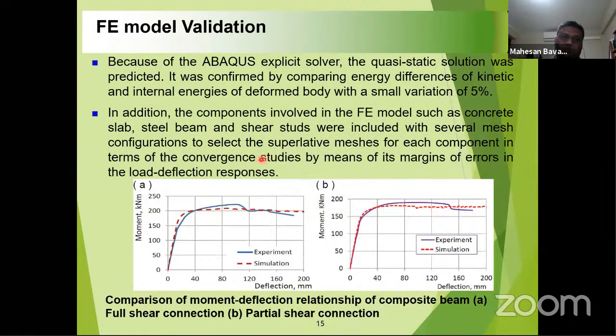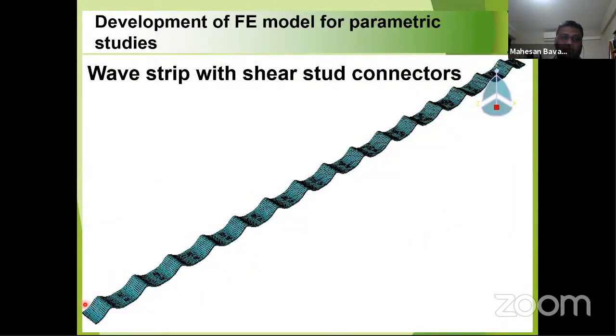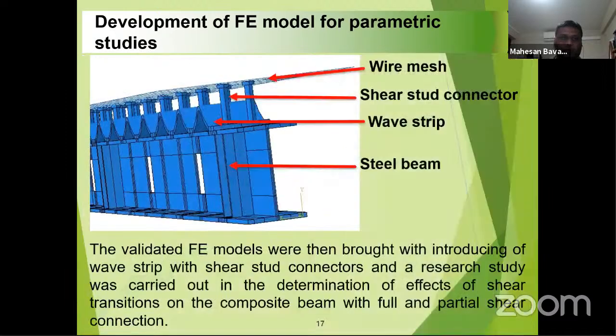Based on the prediction for the full shear connection and partial shear connection, they are very close to each other. It's only 1% to 2% deviation from the experimental analysis. So we conclude this model can be used for parametric studies. Then, to address the gap in the research, we introduced this waveform steel strip to the composite beam. So we introduced this waveform steel concrete composite beam wave strip in addition.